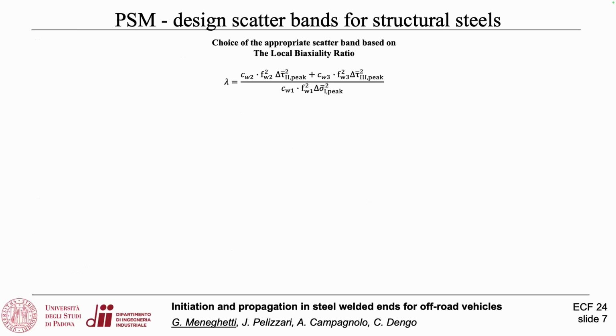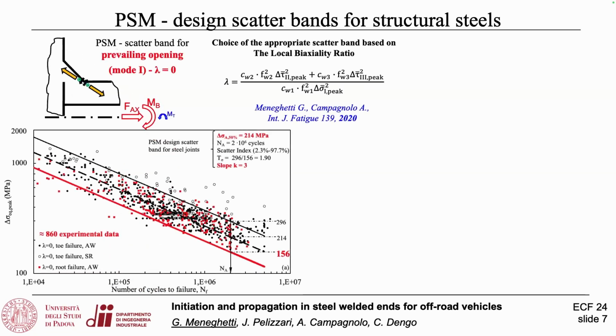As you see here, the local biaxiality ratio weights the shear mode contribution to the linear elastic strain energy against the mode 1 contribution. So if lambda is equal to 0, this means no shear modes in the linear elastic strain energy. For example, pure axial loading or pure bending loading applied to the fatigue of welded joints. You can take a slope of 3, and this is the design curve for different survival probabilities.